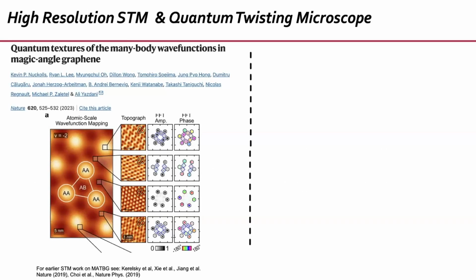One is this very recent study, this past year, by Ali with scanning tunneling microscopy. Ali and his group members took these images of very high quality magic angle twisted bilayer graphene. This is many nanometers by many nanometers, and you can see the moiré pattern, the AA regions, the AB. But they took these images with atomic scale precision so that they could look at the wave functions at the atomic scale. It turns out the different many-body phases of magic angle twisted bilayer graphene, for example the correlated insulators, have an imprint locally on the atomic scale wave function. So in this study, Ali and colleagues could narrow down, among the many, many options for correlated insulator states in the system, very severely, so that there's now a very good amount of data for theorists to continue thinking about this problem. And this was really very interesting.